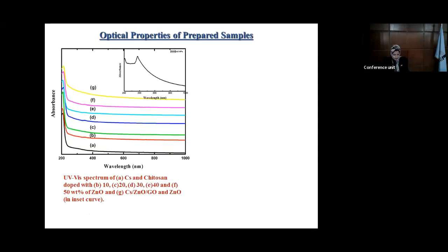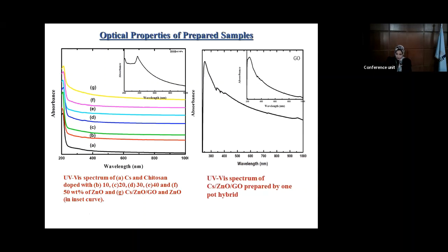The UV spectra of chitosan zinc oxide and the composite of chitosan zinc oxide graphene oxide showed a maximum absorption band at 206 nanometers for chitosan. There is a shift in the peak of chitosan toward the longer wavelength. The move toward the longer wavelength suggested that the doped sample will have a small band gap.